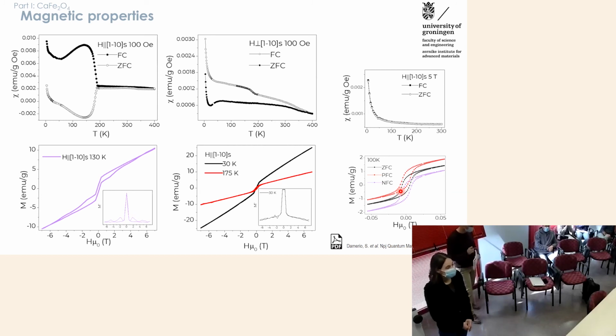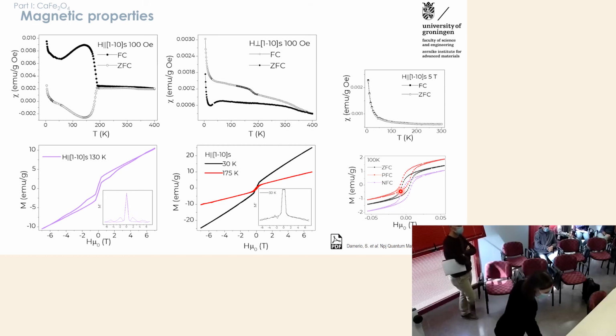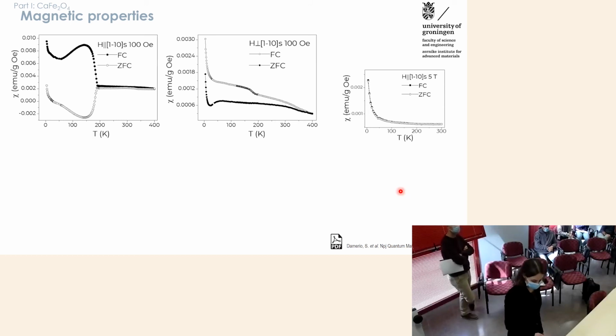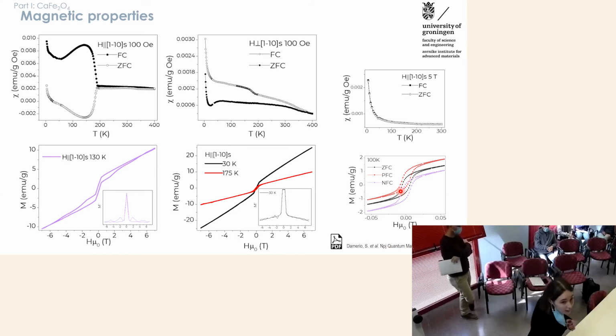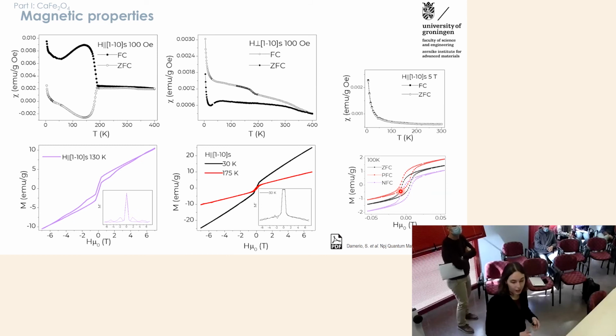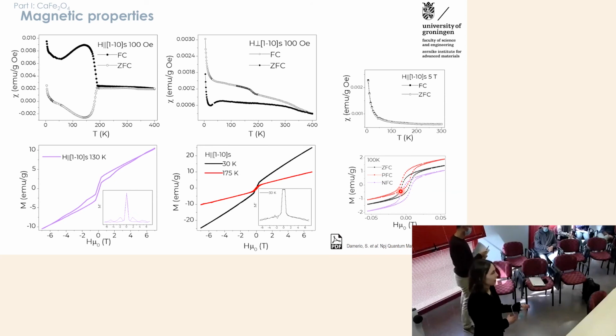Thanks for your talk. In the introduction, you mentioned from neutron scattering experiments this discrepancy between powder and single crystals regarding the possible A or B spin orientation. So, in light of your experiments, what can you say about that in your film? Yeah. In light of this, what we can say is that for sure, only one of the two is the ground state, at least in the films. This system doesn't have two ground states. One of them is the ground state that forms at the Néel temperature, and the other one comes from the formation of these antiphase boundaries.